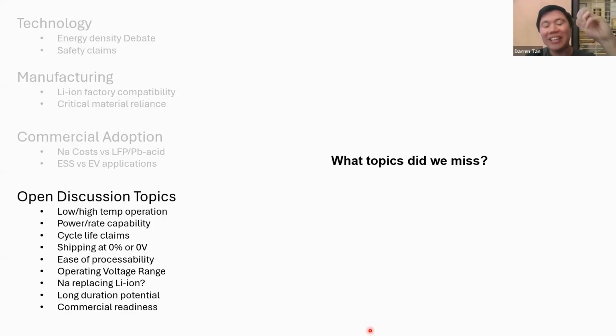It takes lithium slower and releases lithium slower. And if you do it too fast, you can cause plating and nasty things to happen. But once you swap it out for hard carbon, suddenly everything moves at like lightning speed. That's why sodium ion is great for fast power or high power applications.